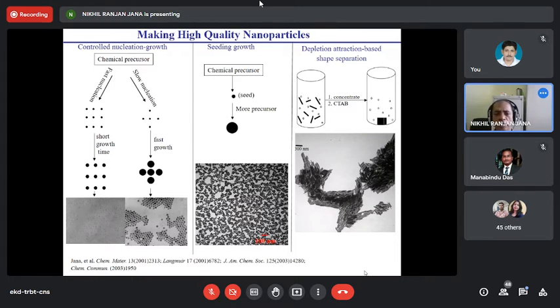But in the same solution, if you add a very strong reducing agent, so that so many nucleation centers are formed, and you don't have much precursor either, all will be exhausted very soon. Then growth will be very short, so you will end up with small particles. So small versus large particles you can make by these approaches. And the middle one is seeded growth. You first make a small seed, grow it into larger size in presence of precursors. And you can stop at different sizes depending on how much precursor you added.